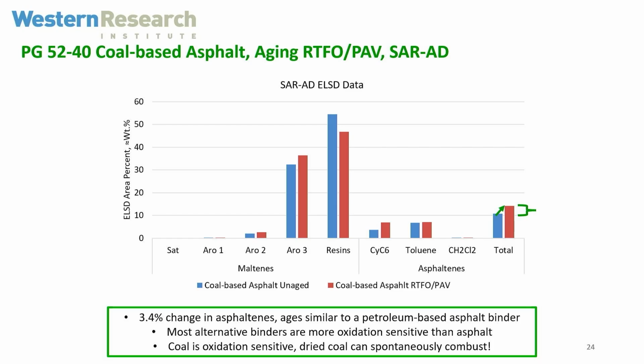And for me, this was amazing that we could overcome this challenge because I don't know if you know, but Powder River Basin coal is full of water. And then once you dry it out and you can put it in a silo or use it in a lab, or you can dry it out really well and you can pull it out of the oven, it might smoke on you. And in some cases, it can spontaneously combust, because it really wants to react with oxygen. So by doing the chemistry that we've done, we've mitigated this problem that's kind of inherent to these coal molecules as well.